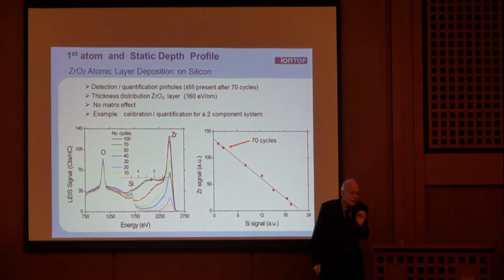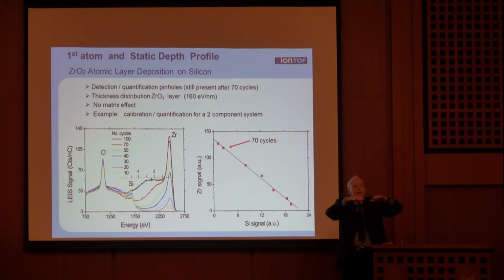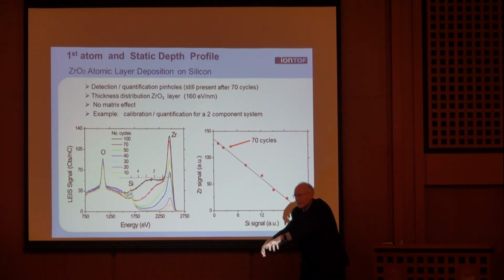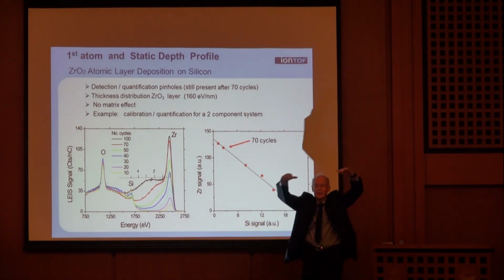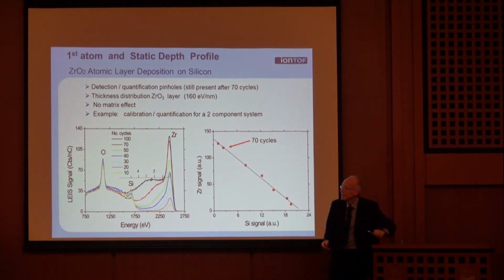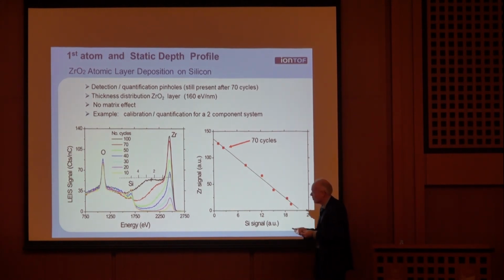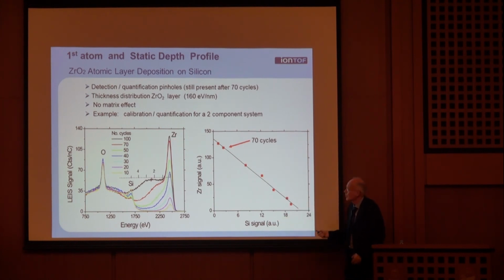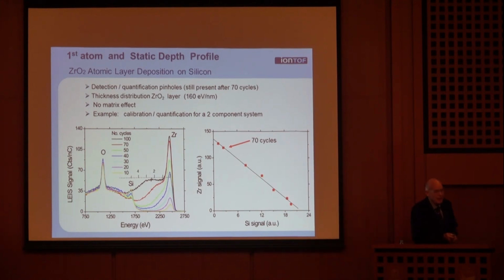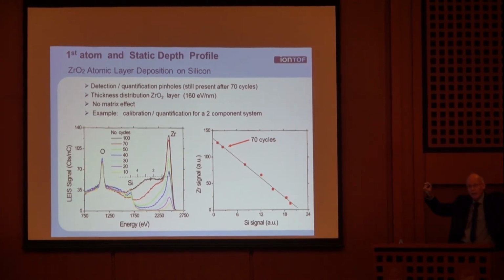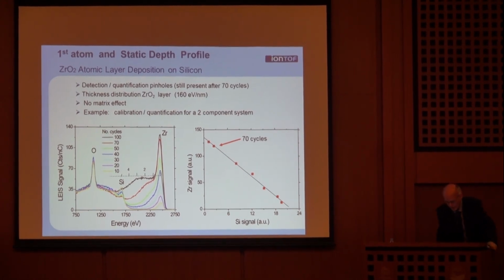Why is there a tail? Because there is not only zirconium in the top layer, but also in deeper layers. So it starts to nucleate in various places, grows in hills, and finally, only here, after 100 cycles, it is fully covered. And so we use that to learn about growth processes and to help especially the microelectronics industry to get very well-defined ultra-thin layers.